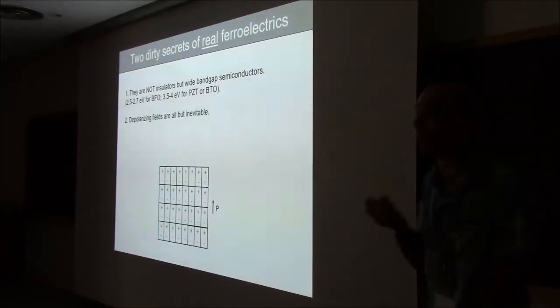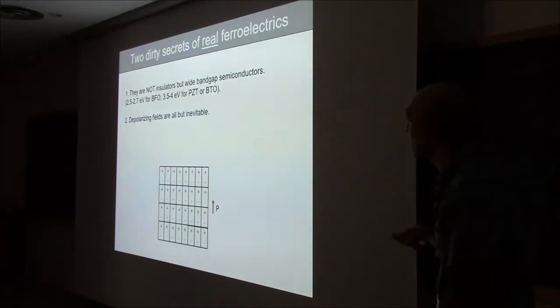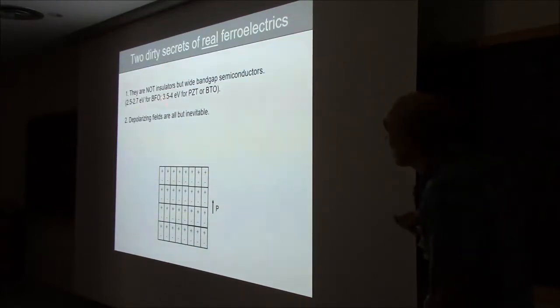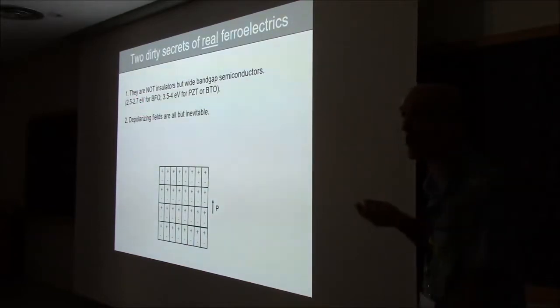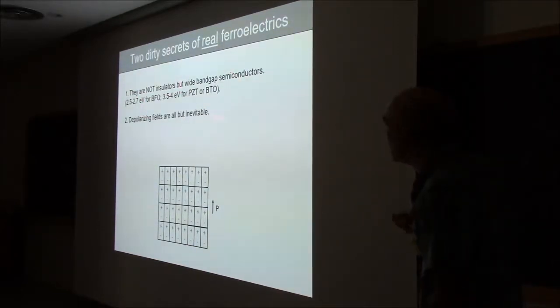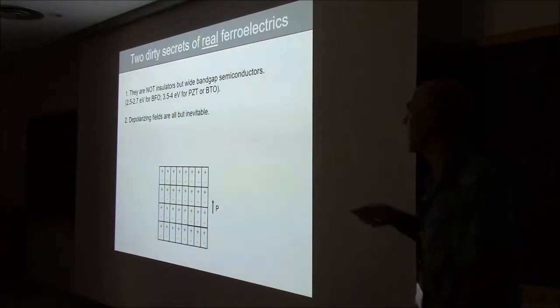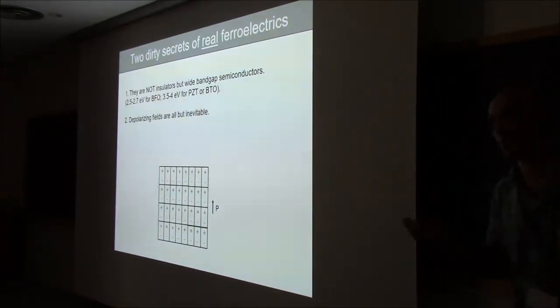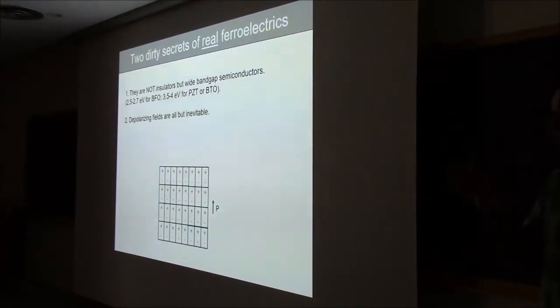In fact, they are not perfect insulators. They are usually wide bandgap semiconductors, or at least the perovskite ones. So the most famous ones are Bismuth Ferrite, which will be familiar to some of you, that has a bandgap of about 2.5 or 2.7 eV. PZT, barium titanate, strontium titanate, all of these things have bandgaps of the order of 3.5 eV, 4 eV max. Okay? They are semiconductors.